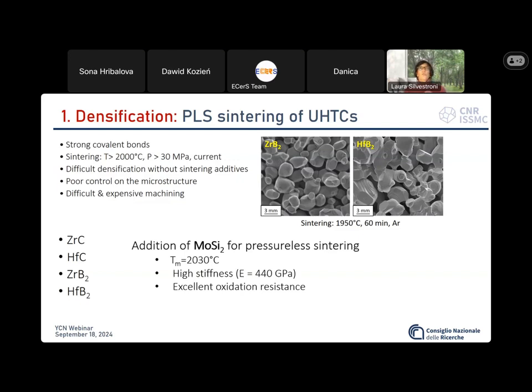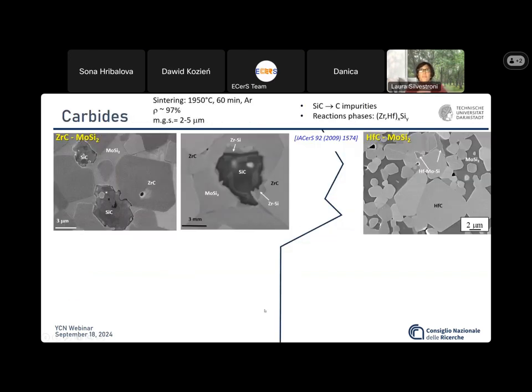Our goal was to enable the densification without application of pressure, so that we can produce near-net shaped components by pressureless sintering. Molybdenum disilicide has a high melting point, high stiffness, and excellent oxidation resistance. These are examples of the microstructures of zirconium carbide or hafnium carbide with molybdenum disilicide that were sintered in flowing argon at 1950 degrees C.